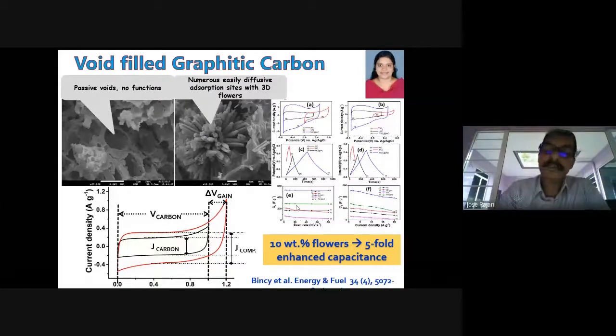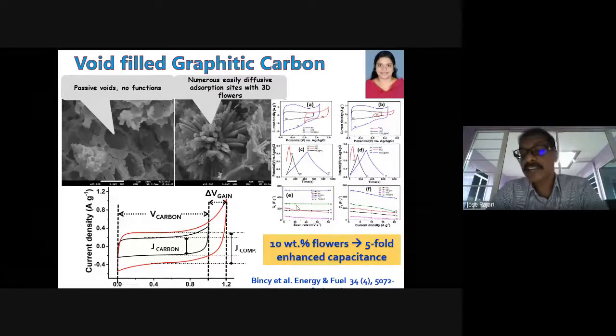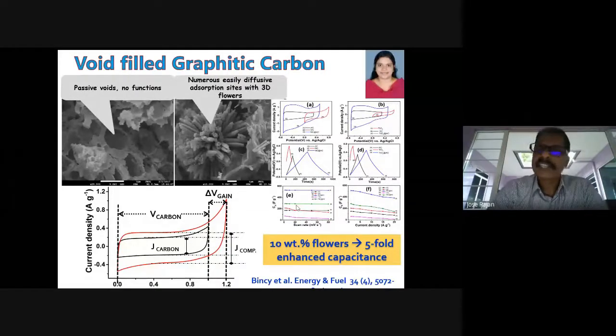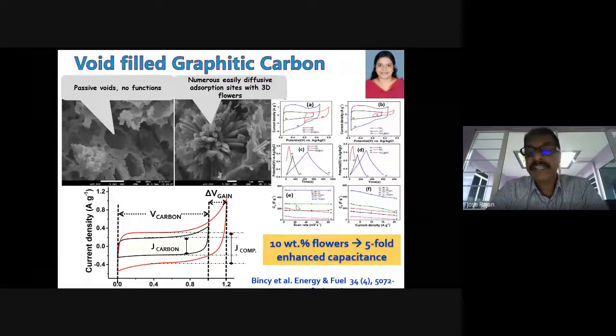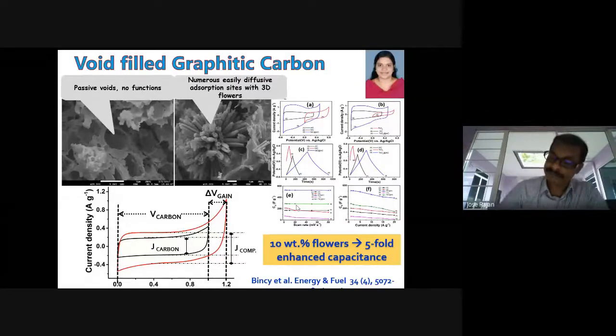And for the ceramic fillers, we used different types of ceramic. One of them is titanium dioxide. Titanium dioxide is also highly abundant on the planet. So by filling these voids with ceramic nanoflowers, in terms of the voltage window, we got higher voltage than pure carbon and higher storage capability than pure carbon.